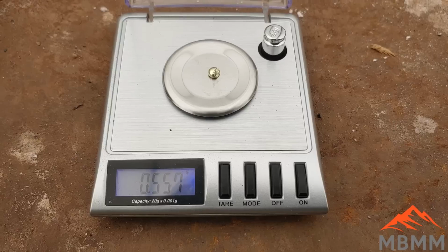And so here by accident, I've really kind of found out a way to counteract that copper sulfide by adding more lye to the smelt and also iron. And I think what happens is the copper sulfide turns into copper hydroxide, which is then actually reduced by the iron metal, which goes from iron metal to iron hydroxide and copper metal. And that collects down into our button, and that's why our lead button weighed so much more.